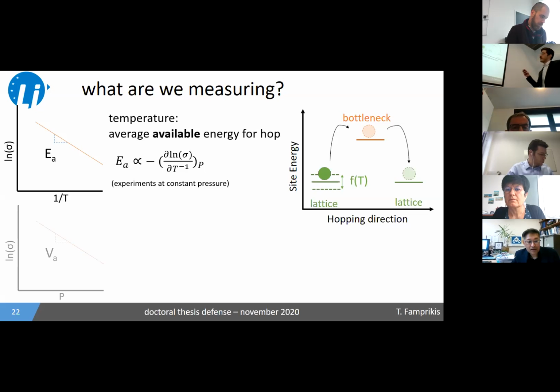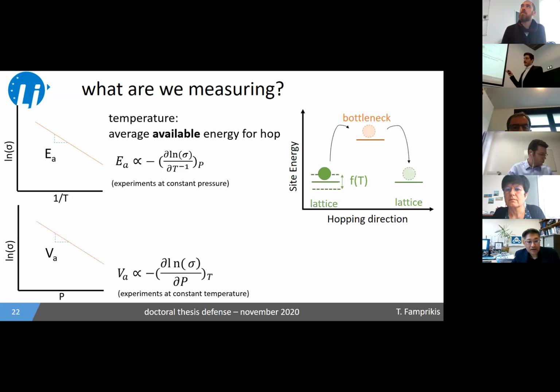And we can think of it in the same way for pressure. We can plot the variation of conductivity as a function of pressure. Again, we have a straight line. From the slope of that, we can get another activation parameter, which ends up being in units of volume. So we call it the activation volume.